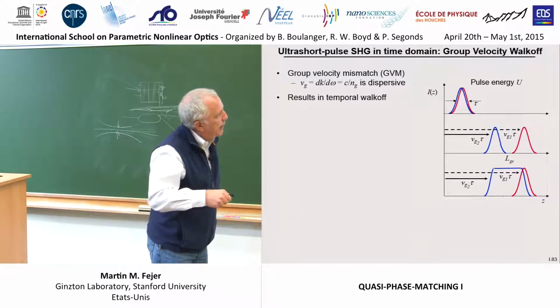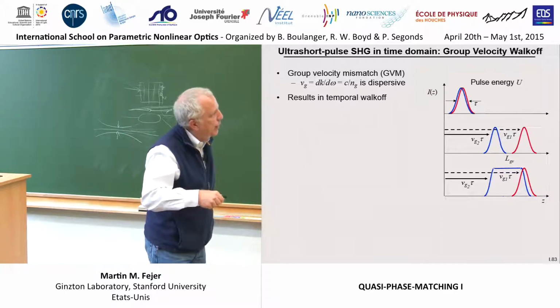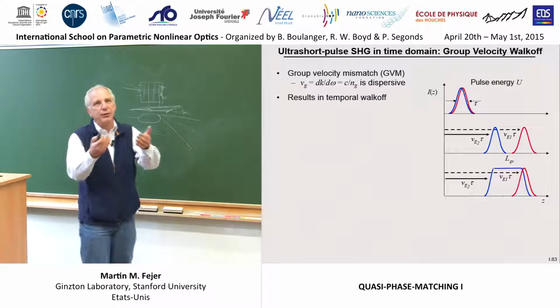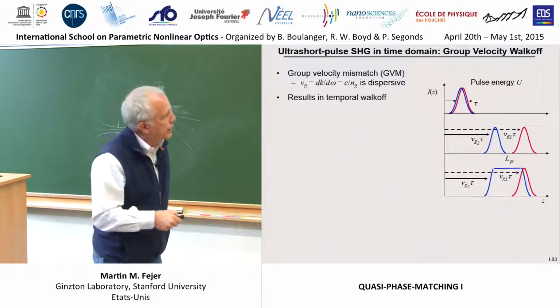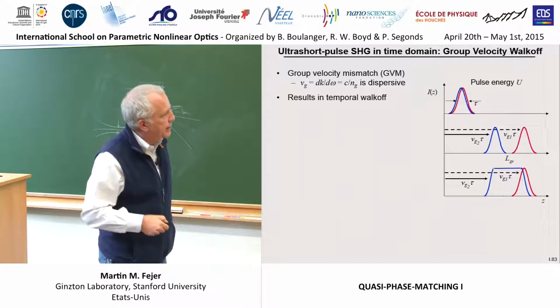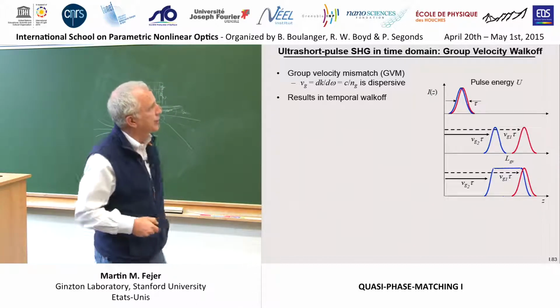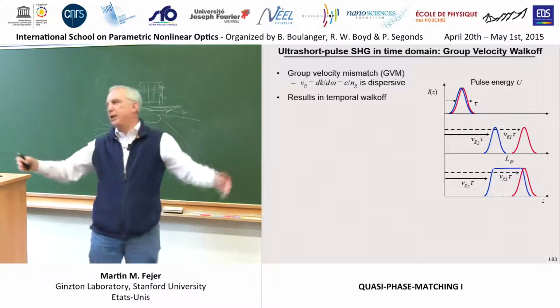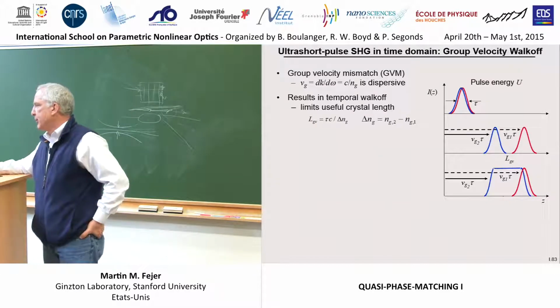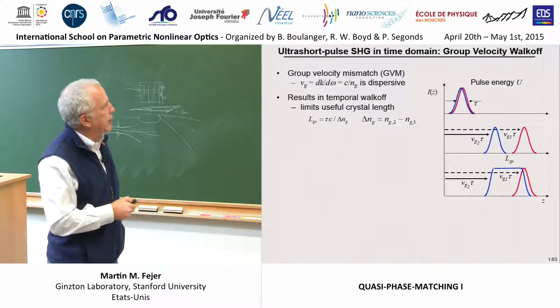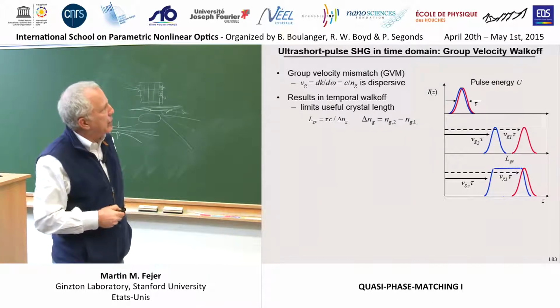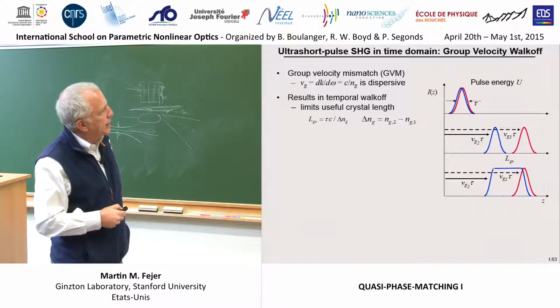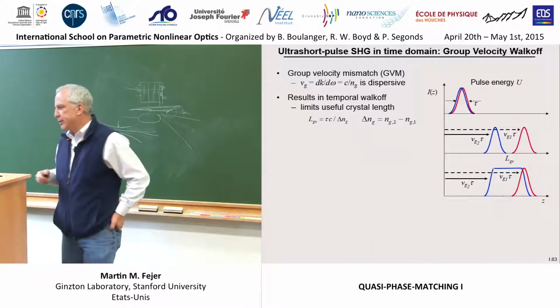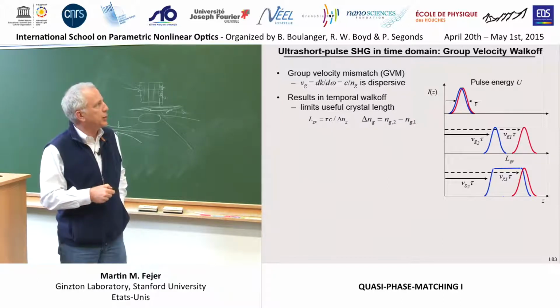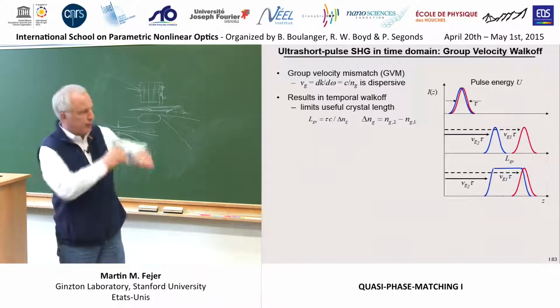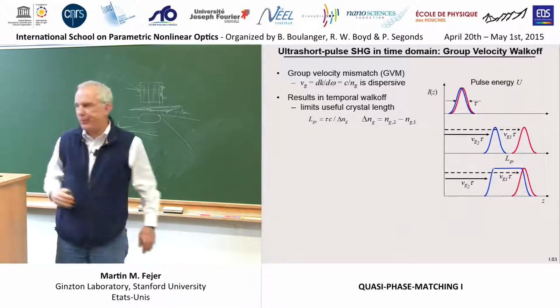And so what actually happens is the pump leaves a trail of second harmonic behind itself as it moves through the medium, and the length of this thing depends on the distance you travel and the difference in the inverse group velocities. So you'll make kind of a flat top trailing behind your pump pulse if the crystal is too long. And you can define a characteristic group velocity walk-off length, which depends on the difference in the group velocities and the duration of the pulse. Larger group velocity mismatch or a shorter pulse leads to a shorter distance before the pulses separate by something like their duration.